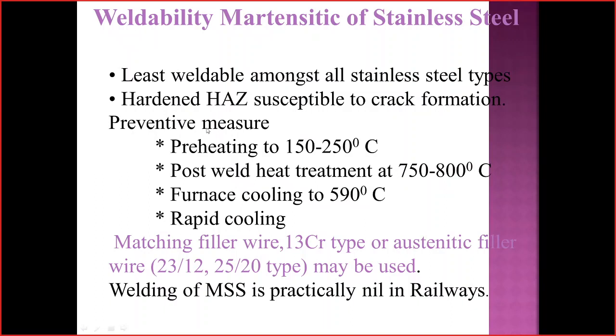To minimize the HAZ, consider what happens if there is more HAZ. More heat affected zone means we are unnecessarily disturbing the original grain structure of the material. If the original grain structure is disturbed, the metal slowly becomes weakened and brittle. To avoid that difficulty, we have to take some measures. One preventive measure is preheating from 150 to 250 degrees centigrade. Second is post-weld heat treatment at 750 to 800 degrees centigrade. Third is furnace cooling to 590 degrees centigrade. Rapid cooling can also be done after completion of welding.